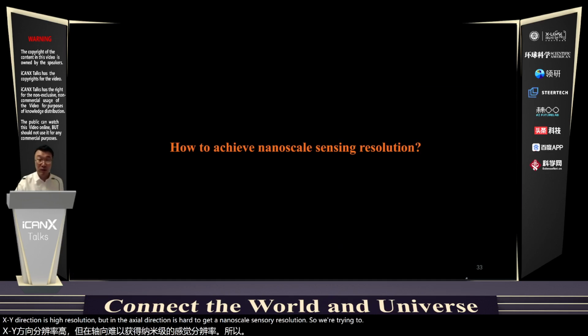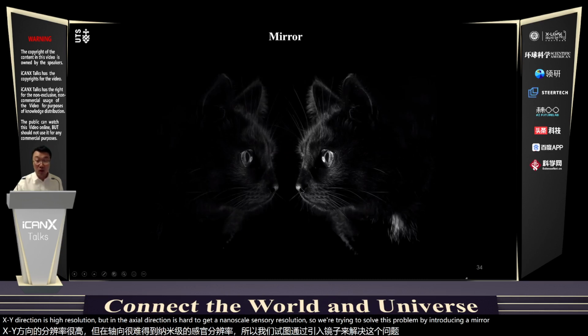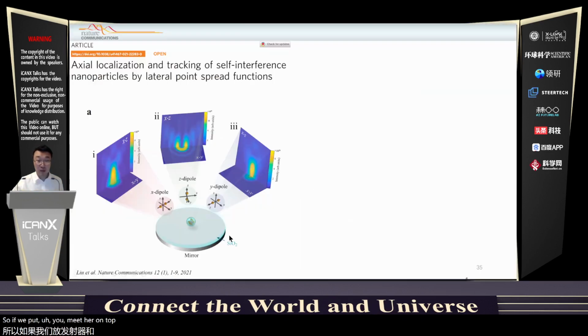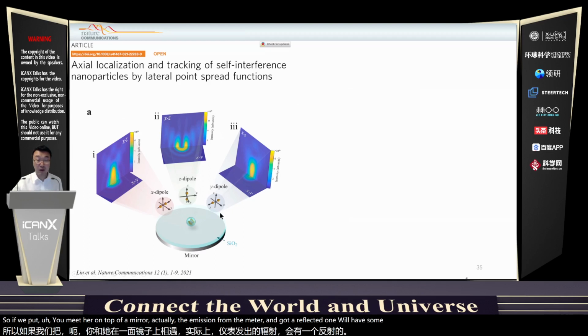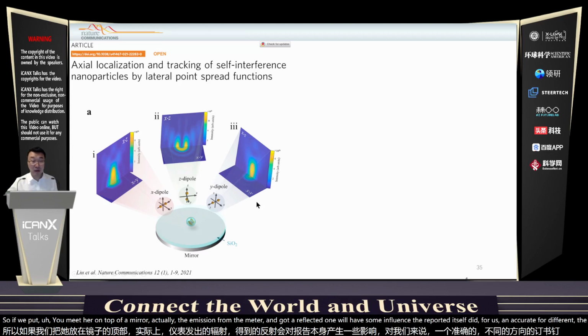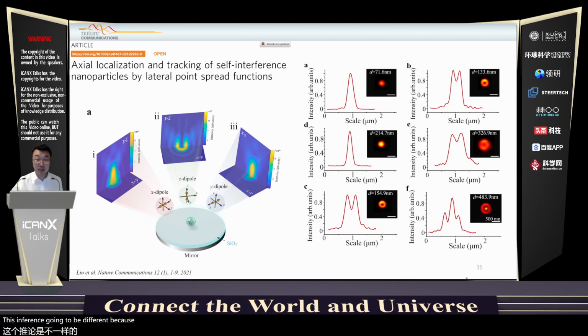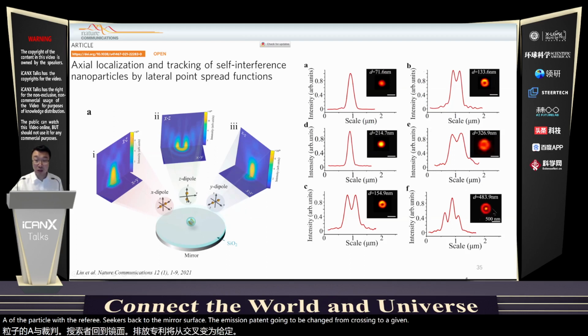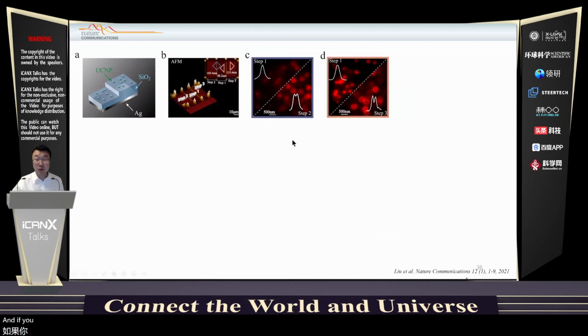So we try to solve this problem by introducing a mirror. If we put an emitter on top of a mirror, the emission from the emitter and the reflected one will have some interference. We call it self-interference. For different dipole directions, this interference is going to be different because of different phase. And interestingly, because different distances give different phase, if you change the position of the particle with respect to the mirror surface, the emission pattern changes from Gaussian to a donut and then to a target. If you put those particles on different surfaces, you can do distance sensing.